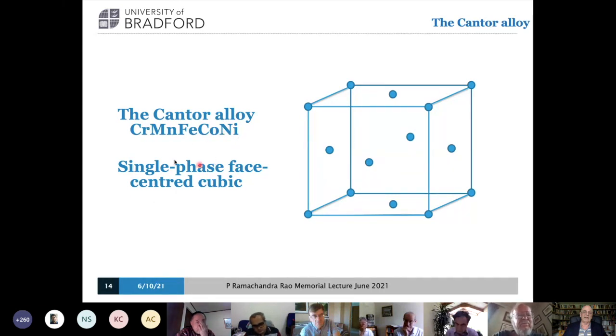So let me explain for those who aren't material scientists what face-centered cubic means. It means the atoms are arranged like this. An atom at each corner of the cube and an atom in each face center, fairly obviously. And this is the structure that many of those soft metals have. Pure copper is face-centered cubic, pure nickel is face-centered cubic, pure gold is face-centered cubic, pure lead is, pure aluminium is. And it's because of that that they have this softness and this ability to be deformed and also this resistance to fracture. It's because in this structure, the atom planes can roll over each other rather easily, and so you can get a change of shape in the material rather easily without it fracturing. So they're resistant to fracture, and they can also be shaped very easily. And it's because of this structure.